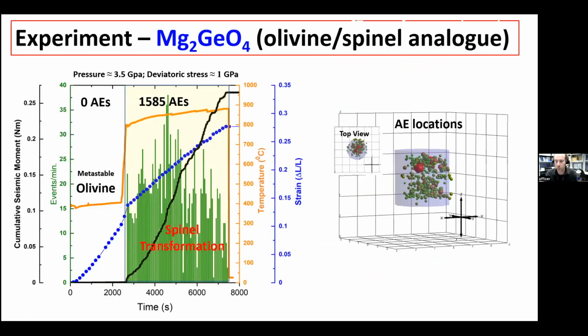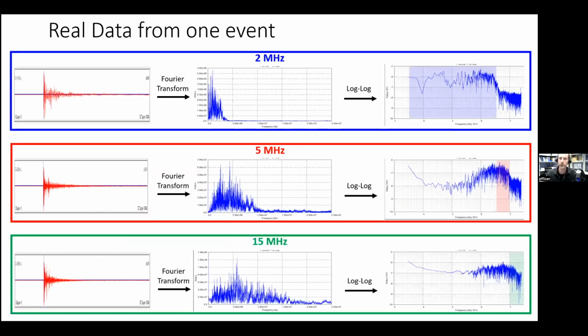And then of course, in order to get acoustic events, you have to run an experiment. So this is the same data as before. We broke a piece of Mg2GeO4 under high pressure, so we have acoustic events. So this is just showing some frequency spectra. So here are the acoustic signals. Here's the Fourier transform of them. And you see that the higher frequency transducers pick up higher frequencies, not too shocking.